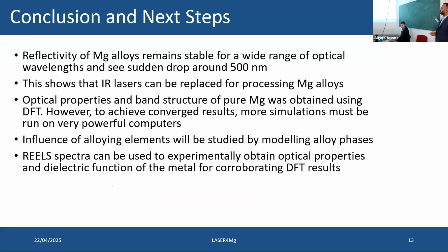So in conclusion, I would say that the reflectivity of magnesium alloys is pretty much constant for a very wide range, and it starts to drop around 500 nanometers. It shows that the IR lasers can be replaced, and better laser systems can be developed or bought straight away to do processing of magnesium alloys. And I have to use high performance clusters to perform the DFT simulation to get a better understanding and more converged results. The influence of alloying elements will be studied, and that will be compared to the results of REELS spectra.